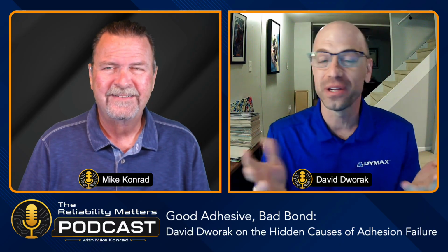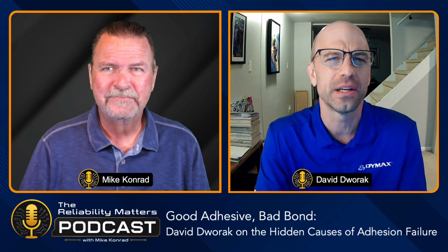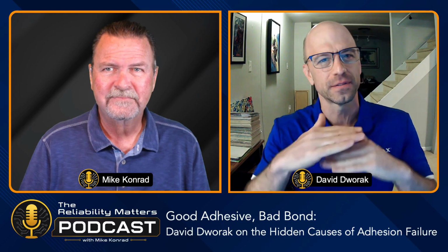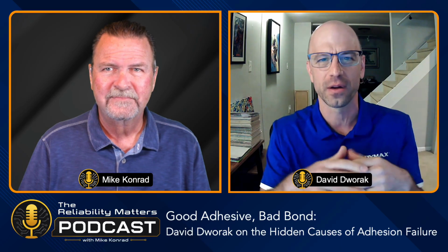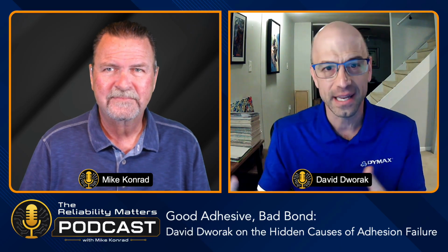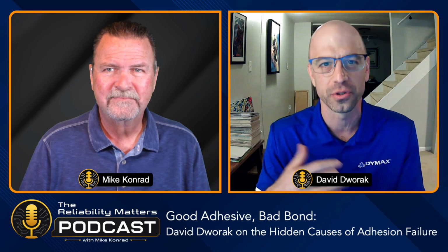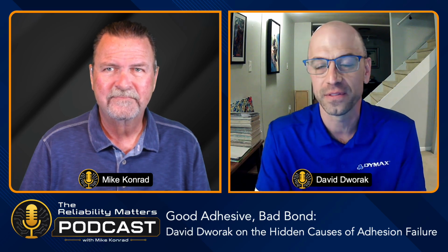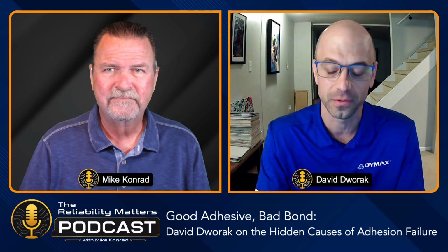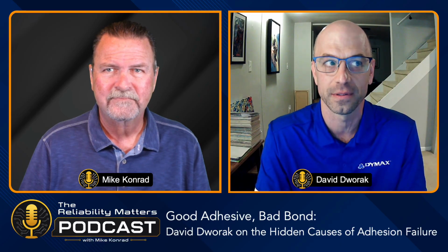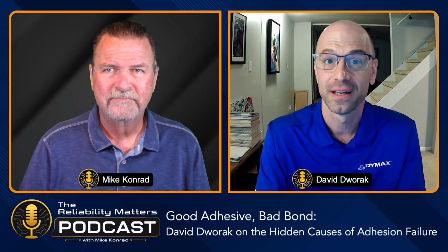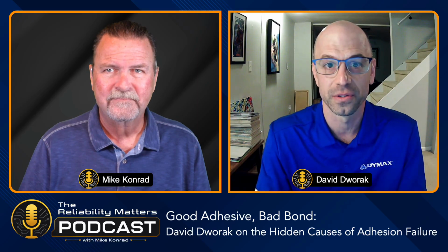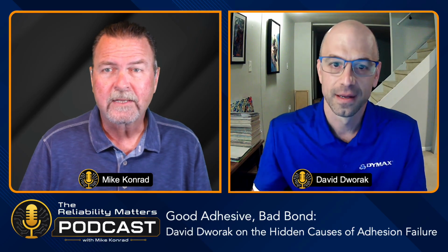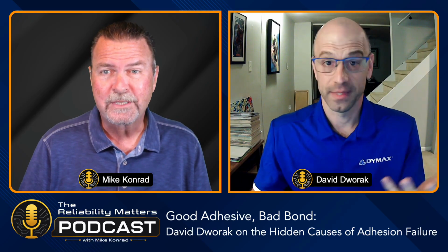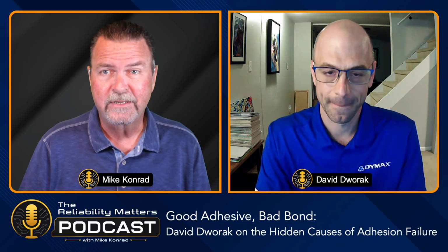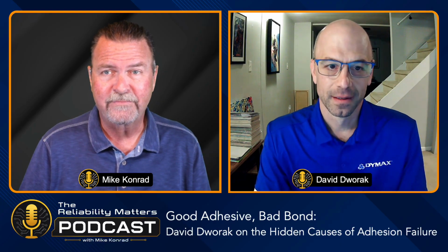And you might find you're only curing your adhesive maybe 80 or 90%. That's enough to hold it together and move it around and give you good green strength. But in the end, when you finally put that assembly through your testing, that extra 10, 15, 20% cure is absolutely a massive amount of percent cure to be missing, and your adhesive is just going to fail. Right. It might be enough to get it out into the shipping department, but once it's put into the real world with shock and vibration and other elements, it fails.